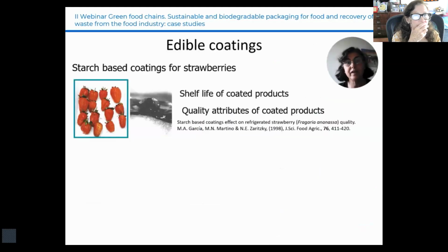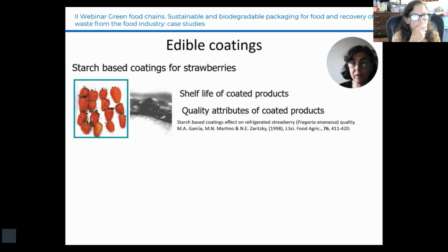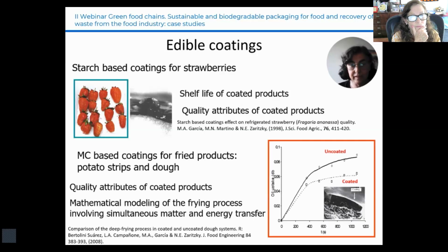We decided to begin our research with edible coating, a challenge since the formulation development has to be adaptive to the requirement of the product being coated. In particular, we chose strawberry, a highly perishable fruit with a very short shelf life. We optimized the formulations and the application method for the coatings, which had to be imperceptible to ensure consumer acceptance. We verified the uniformity of the coating by iodine staining and achieved a shelf life of 21 days for the coated products, more than 7 days longer than the control. I've included some of the published work on this topic in case of interest.